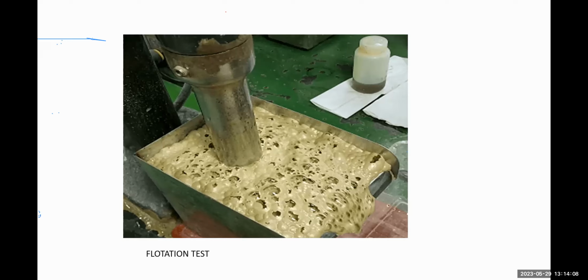So those are just a chemical aspect of it. But look at it now. There are foams that are forming. So it is the mineral now that is coming on the surface, because it has a very high degree of buoyancy. And because you have been able to maneuver the surface chemistry to make some of them stay in solution, and also to make some of them come out of solution, you have been able to play around with the chemistry of this surface material. Then you're having this floater coming out, and then you scrape it out.